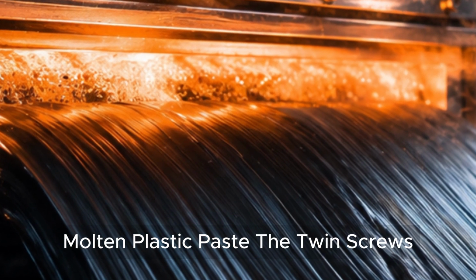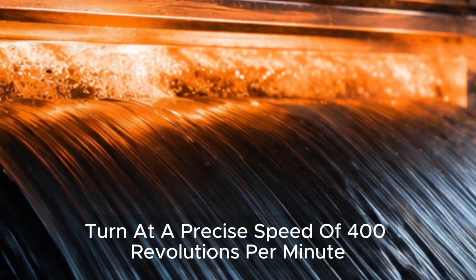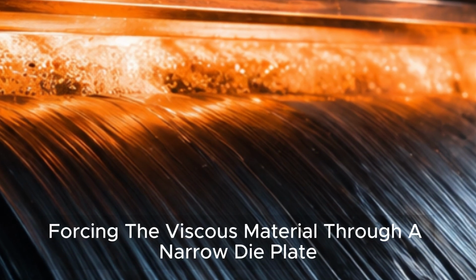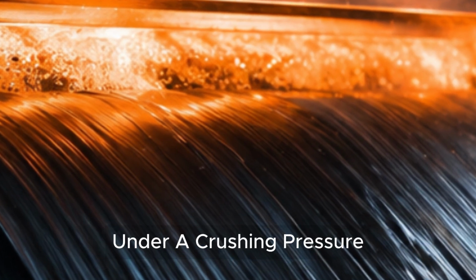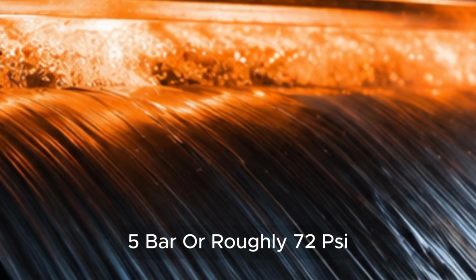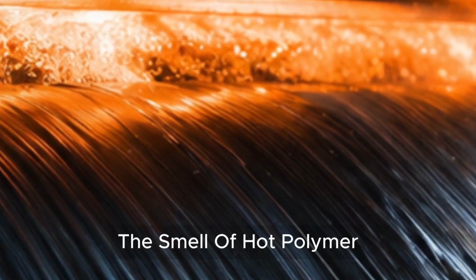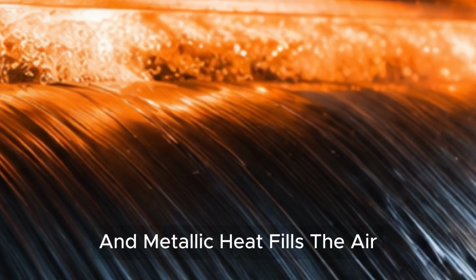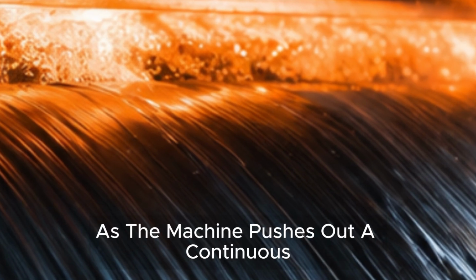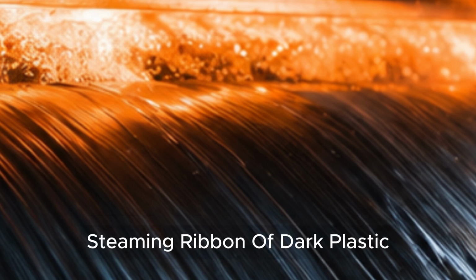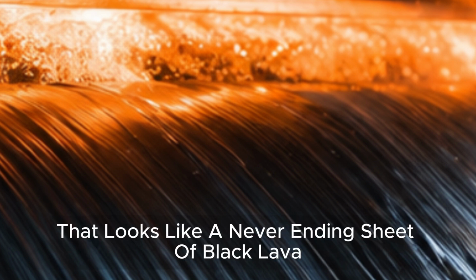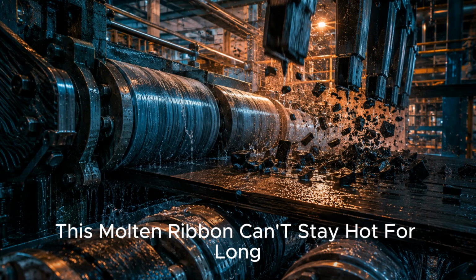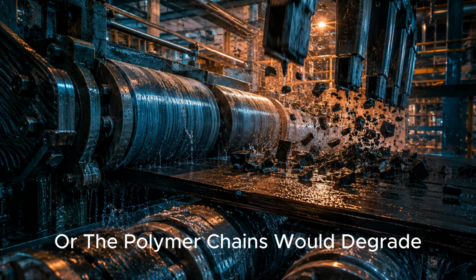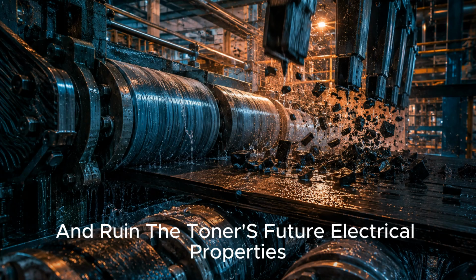The twin screws turn at a precise speed of 400 revolutions per minute, forcing the viscous material through a narrow die plate under a crushing pressure of 5 bar, or roughly 72 psi. The smell of hot polymer and metallic heat fills the air as the machine pushes out a continuous, steaming ribbon of dark plastic that looks like a never-ending sheet of black lava. This molten ribbon can't stay hot for long, or the polymer chains will degrade and ruin the toner's future electrical properties.